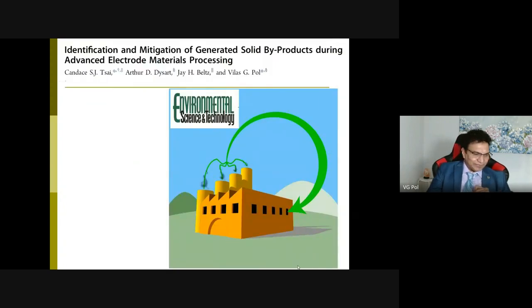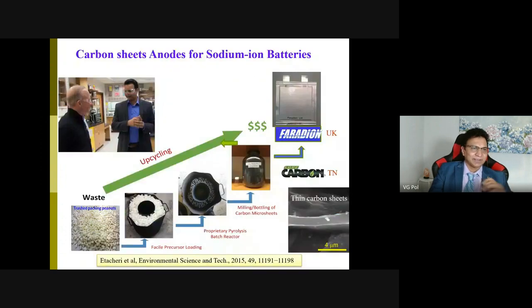Now, since we are talking about the environment, we also checked, when we make something on a larger scale, whether we are releasing some carbonaceous material to the atmosphere, just like shown here. This is a cover art of the journal published in Environmental Science and Technology. Actually, those particles we were not able to see, but we were releasing some of the particles in our initial stage. So we decided to trap those particles and put them back into the system under argon or nitrogen atmosphere, making the whole system green and nothing released to the atmosphere, no carbon dioxide, no carbonaceous material that can harm the society.